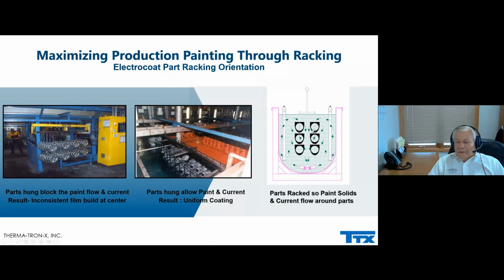A lot of people make mistakes with this. Here's a rack that's going to go through. Here you see the same product; the electrodes are always located on the sides of the tanks. If you process through a square transfer type system, you want the current to flow through these parts so that you get a lot of solids and a lot of current flowing through. If you load this way, you're blinding off the center ones, and the current has a hard time getting in. What happens is you get inconsistent uniformity on the paint coating.